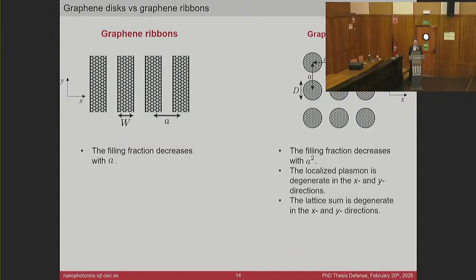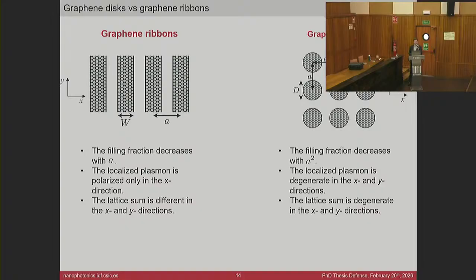Here we have a localized plasmon that is degenerate in x and y directions, where the lattice sum and the interaction is also degenerate in both directions. We know that lattice resonance is coupled through far field direction, which is orthogonal to the polarization. And no matter what polarization we choose, we always have an orthogonal direction in which the array is periodic. However, this is not the case in the array of graphene ribbons. In this case, the plasmon of the ribbons is fully polarized in the x direction. However, the array is not periodic in the orthogonal direction, and this is going to give us problems.